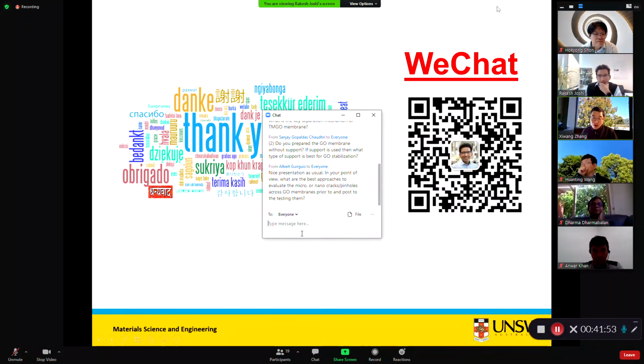His question is, graphene oxide also swells in water and might delaminate during water-based application. Does it not delaminate during water treatment? Okay. Very good question. Yeah, swelling is a problem in graphene oxide, but now using the mild thermal annealing method, we have controlled the swelling. If you do the mild thermal annealing, it doesn't swell anymore. Also, in our patent we use a cross-linker to PVDF, and then it doesn't delaminate.